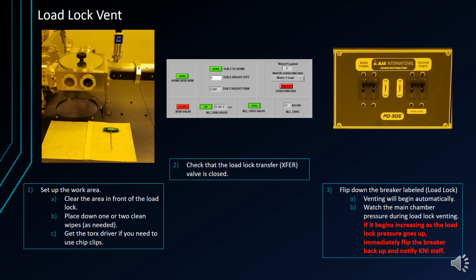Note, as the venting starts, pay attention to the main chamber pressure and the load lock pressure. If the main chamber pressure begins to rise, you must immediately flip the breaker back up to stop the vent and begin pumping instead. This happens if a flake of metal or sometimes a small piece of a wafer gets in the way of the transfer valve actuation, therefore causing a leak. If this happens, notify KNI staff and do not proceed. Put on a second pair of clean gloves. From this point on, be careful not to touch anything other than your clean tools and sample boxes, and the handle for the load lock lid.